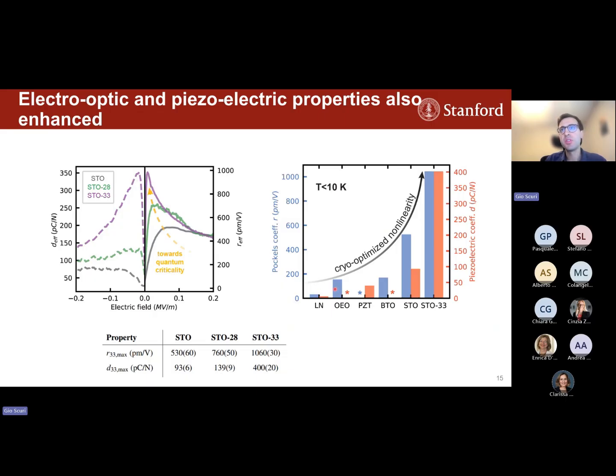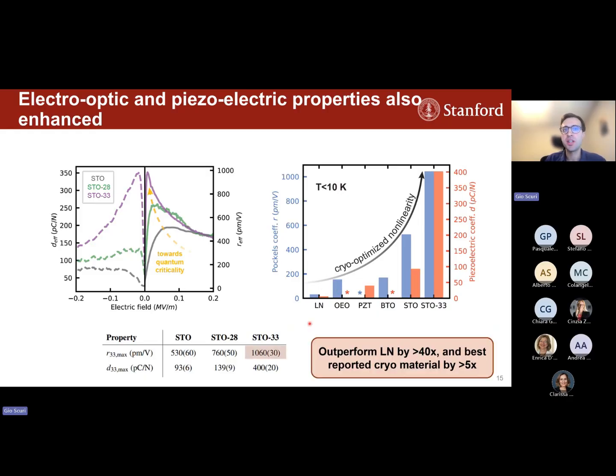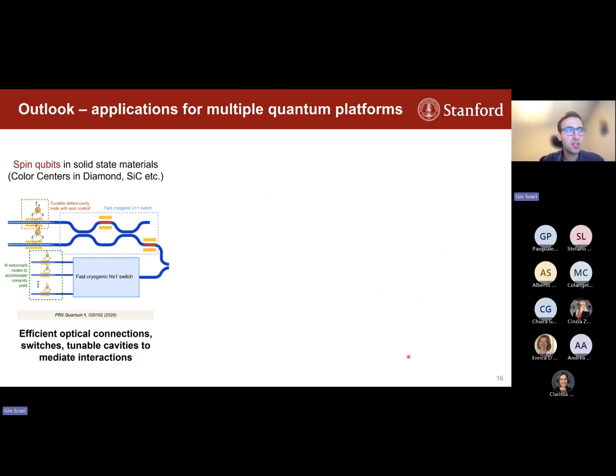And so we really were able to optimize the nonlinearities in the system at these specific cryogenic temperatures, outperforming any known material at this temperature by more than 5 times, and lithium niobate, which is the most used material, by more than 40 times. And as a brief outlook, this advancement in better electro-optic materials is useful not just for this heterogeneous integration.